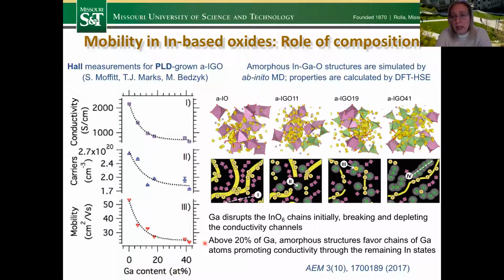And using the simulations of indium gallium structures with different gallium content, what we found, again, is that morphology is likely the cause of this mobility being stable and not going further. So there are competing phenomena that occur. First we have the indium oxide and chains, very good, just no gallium. As soon as we start putting gallium, we are breaking some of the chains. So gallium does disrupt the chains initially, depleting the conductivity channels.